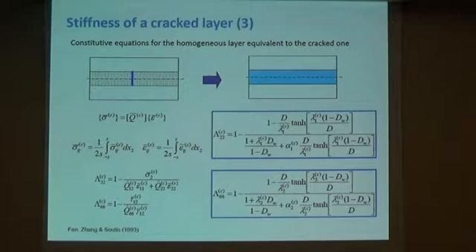For these in situ damage effective functions, we can derive the following closed form analytical expressions that give them in terms of material properties of metal and ceramic, and also in terms of two damage parameters: D, which is the relative crack density, crack spacing normalized by the layer thickness, and Dw, that is the relative crack widening, the width of the crack relative to the length of the segment. And knowing these functions, we can estimate stiffness properties of the equivalent homogeneous layer that can replace the cracked ceramic layer.